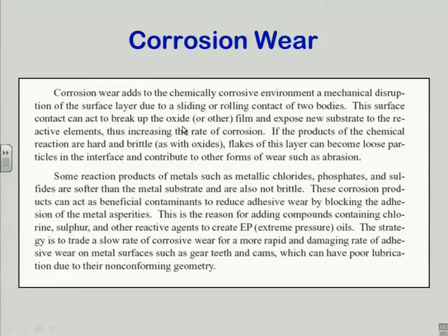And just sticking the part in the corrosion material, or corrosive material, I should say, is enough to do damage to it. But it gets much worse, much faster, if I also apply stress to the part in any fashion. Rub two parts together while they're in this salt water or whatever. Because what happens then is the rubbing together strips the oxide that virtually immediately forms when I put it into the medium. And it then provides fresh fodder. You know, I've got now some nice clean steel available for the corrosive environment to keep eating. So rather than slow down the process by having a whole bunch of corrosive products in the way, I'm getting rid of them and making it happen faster.